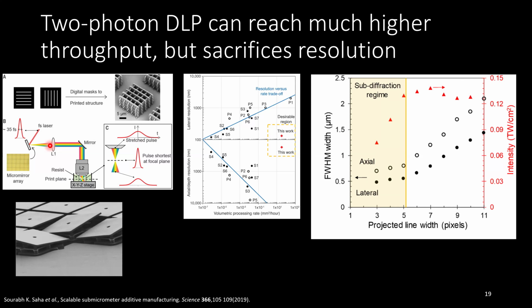Yep. So this is sort of the fundamental problem with this approach in this paper that they kind of buried in the SI, which is that when you're making sort of diffraction limited line structures like this, you get nice diffraction limited resolution. And there's an extra piece here that I didn't mention because it gets a little bit technical, but this DMD also acts as a diffraction grating, and you get an effect called temporal focusing, which can essentially compensate for 1 degree of spatial defocusing. So when you have a diffraction limited line, you basically have 1 dimension of spatial focusing, 1 dimension of temporal focusing.